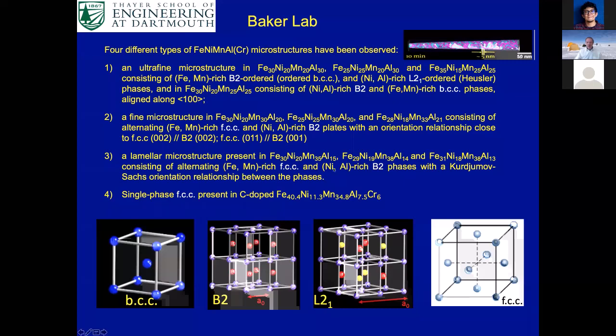Then when we lowered the aluminum content further, we ended up with a lamella structure that was formed by eutectic reaction again, which consists of FCC and B2 lamellae in this case, with a Kurdjumov-Sachs relationship between the two. And then finally, when we lowered the aluminum content further still and added chromium, we ended up with a single phase FCC alloy that we also looked at in the carbon-doped form.